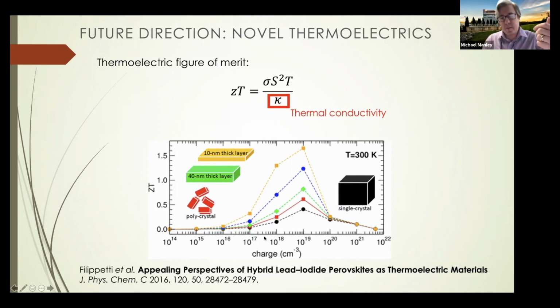This is a recent paper where they looked at possibly using this material, actually methylammonium lead iodide, for a thermoelectric. And they optimally doped it. It's a theory paper, so you can take what you want. But in order to reduce the thermal conductivity, they looked at thinner and thinner layers, and they could push it up to some level. But now we have this knob, where we can decrease the thermal conductivity. Maybe we can get this higher. 1.5 is a pretty high number. I think the record right now is about 2.6. I don't think anything's gotten over 3, but when you get above 3, you start to get into ranges where things become practical. So that's a potential future direction.